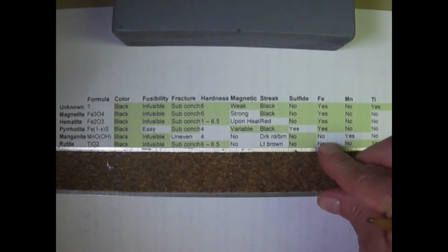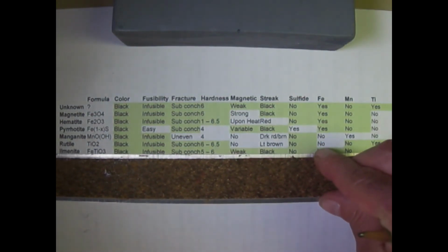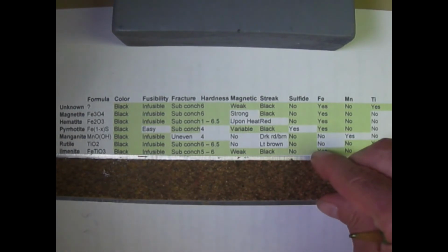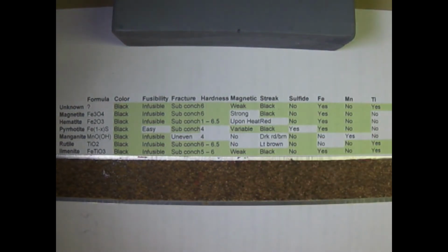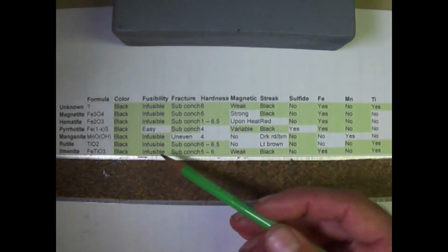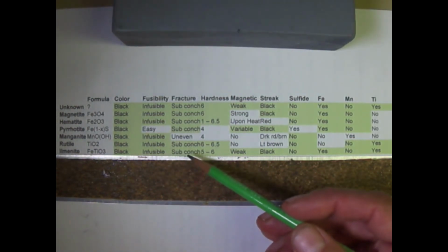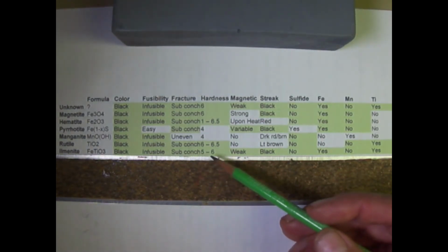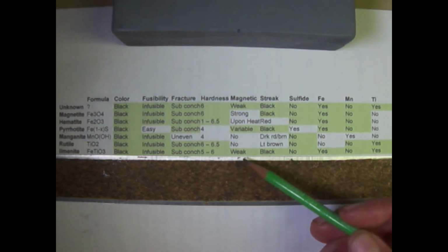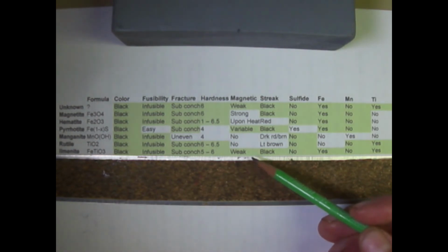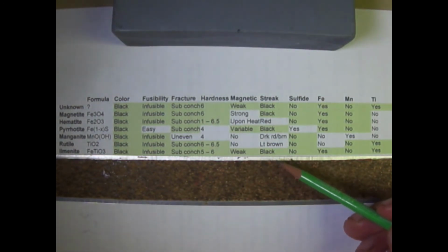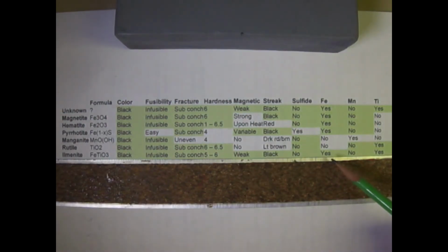So the one last one that I had a hunch about further on down the testing is ilmenite. And it's a black mineral. It's infusible. It has a fracture that would be similar to the subconchoidal fracture pattern. It has a hardness of 5 to 6, so that's within that range. It's actually weakly magnetic, which matches. The streak is black, which matches. It's not a sulfide. It does have both the iron and titanium and no manganese. So there we go. We have our answer.